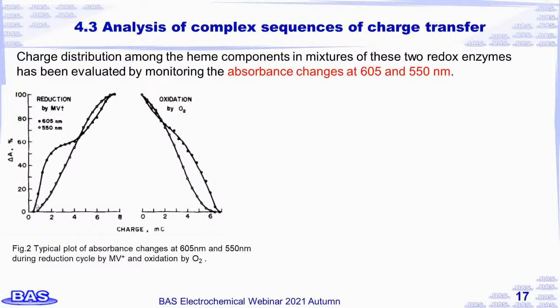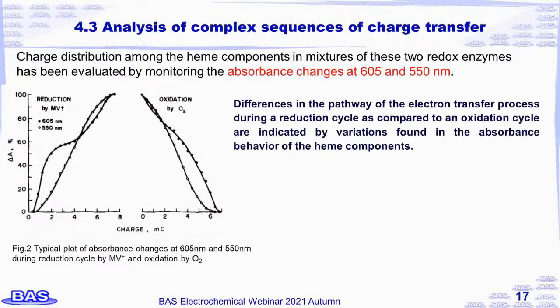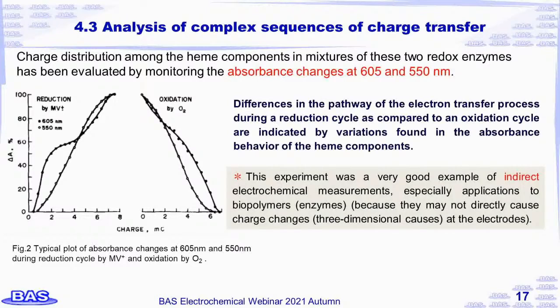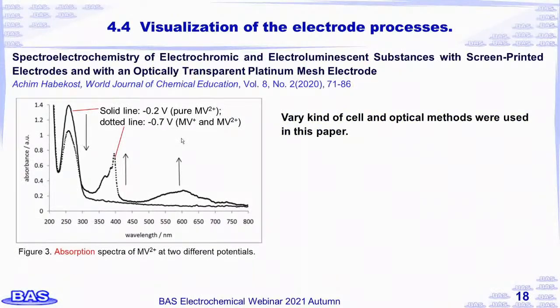It is evident that the oxidative curve of the 605 nanometer band of cytochrome oxidase is not a mirror image of the reductive curve. Differences in the pathway of the electron transfer process during a reduction cycle as compared to an oxidation cycle are indicated by variation found in the absorbance behavior of the heme components. This experiment was a very good example of indirect electrochemical measurements, especially applications to biopolymer enzymes, because they may not directly cause charge changes at the electrodes. The SEC method can visualize the electrode processes.